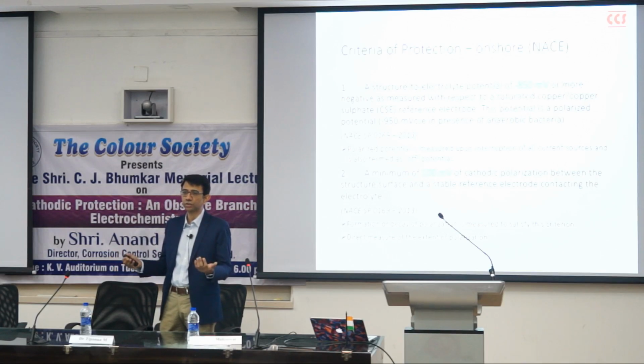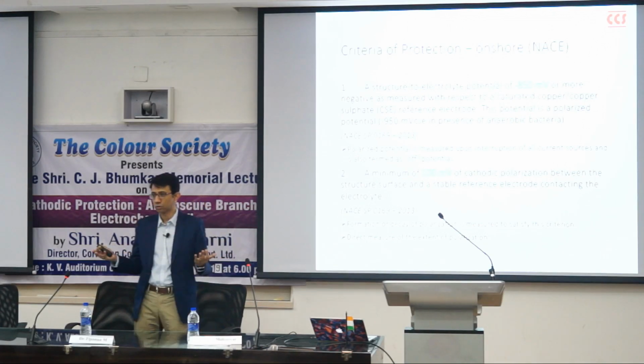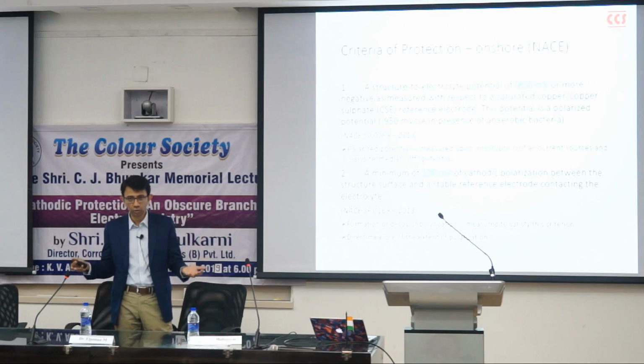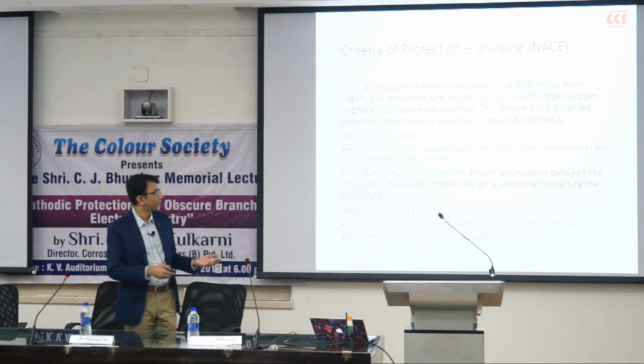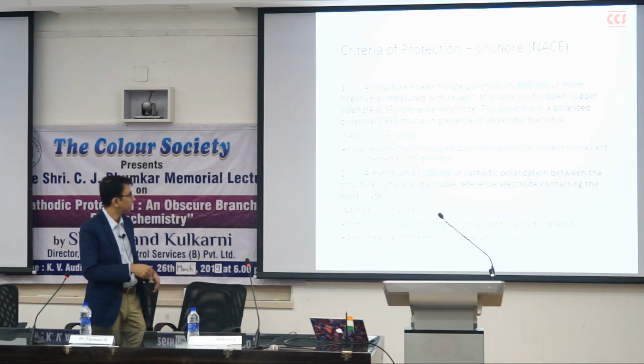And if my structure is not very well coated, say it's a poor coating or it's a bare structure, then I can be safely assured that it is cathodically polarized because there is at least 100 millivolts of cathodic polarization.